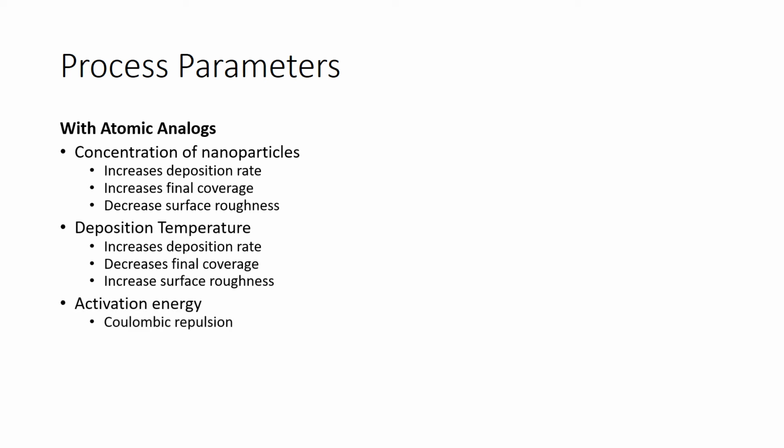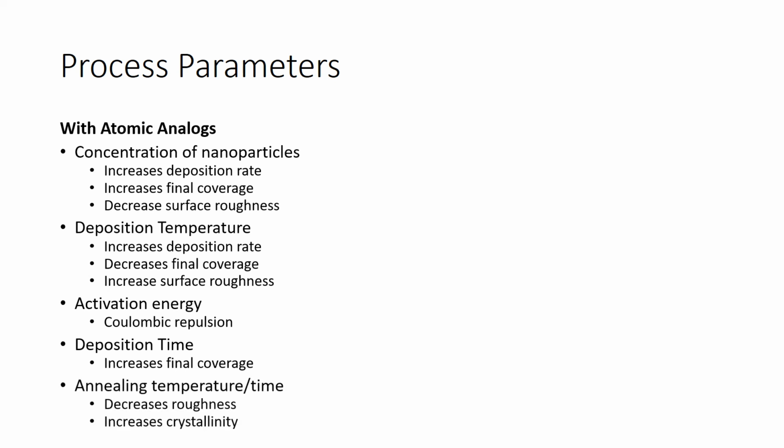We may also control the activation energy. In this system, the activation energy is largely dictated by the Coulombic repulsion between nanoparticles. This may be controlled through a variety of techniques, such as using salt in solution for charge screening. We may also control the deposition time. Generally, the depositions are run to completion. We may also change the annealing conditions, such as the annealing temperature or the annealing time. This annealing step will decrease the roughness of the deposited film and will increase the crystallinity of the superlattice.